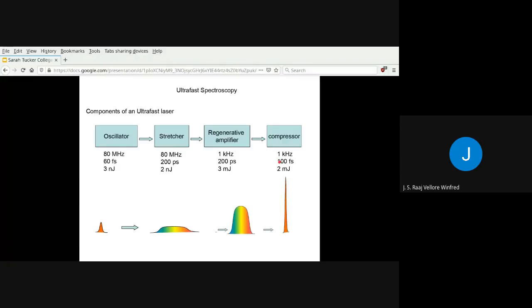And as you can see, the power is very high. We went from 3 nanojoules up to 2 millijoules. That is orders of magnitude more than what we started with. We cannot have 2 millijoules right out because this would damage your optics. That's the reason why you end up having so many steps in order to produce an ultrafast laser pulse.